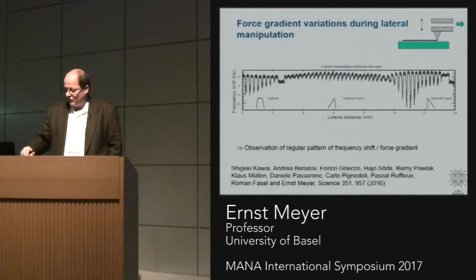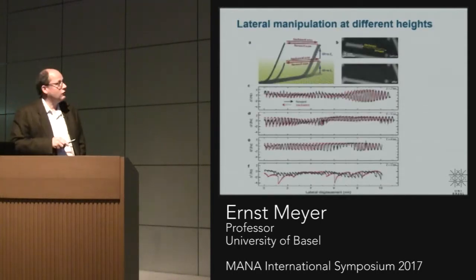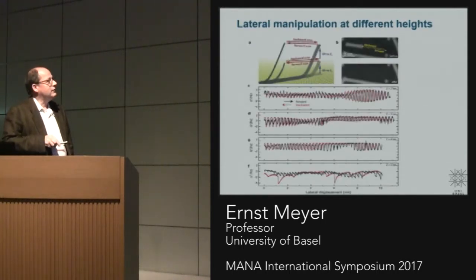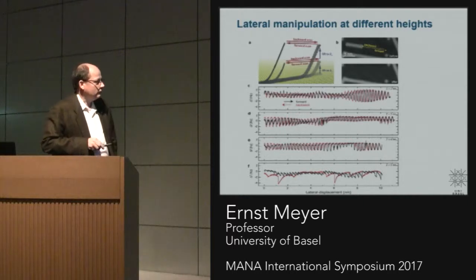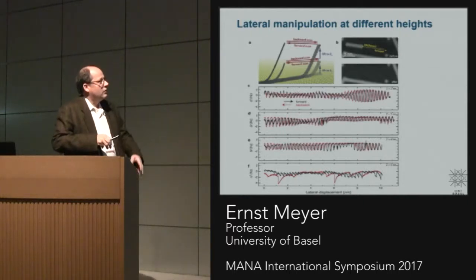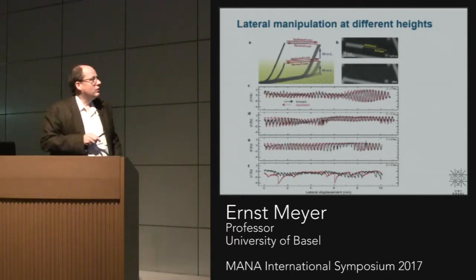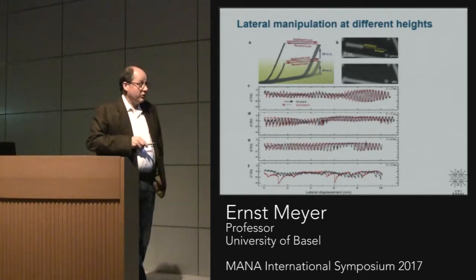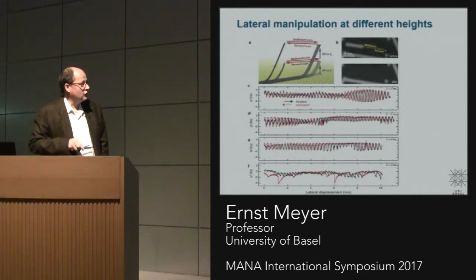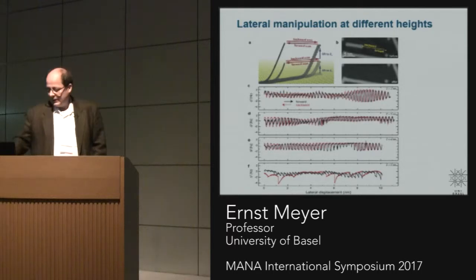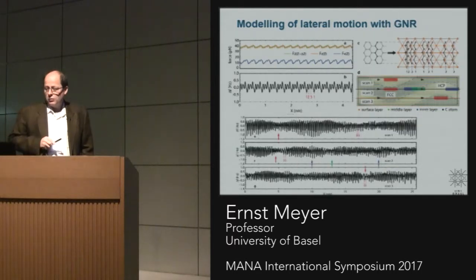And yeah, can do that a bit more systematically, so you can measure at different heights here, and you see there's quite typically you always see this kind of beating patterns here. If you go very far, nearly before the whole chain or ribbon detaches, you also see multiple slips, but that's not so important at the moment.